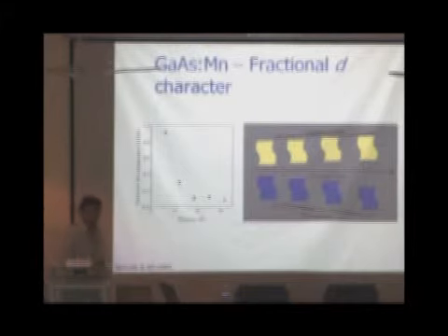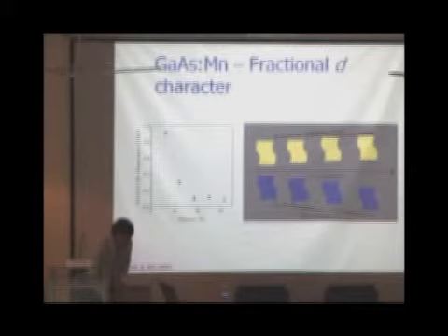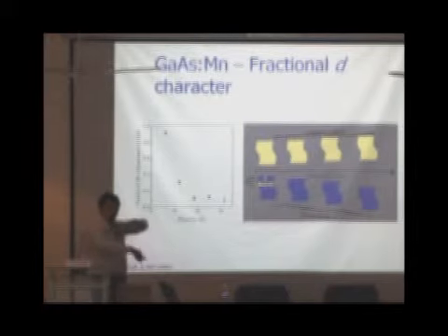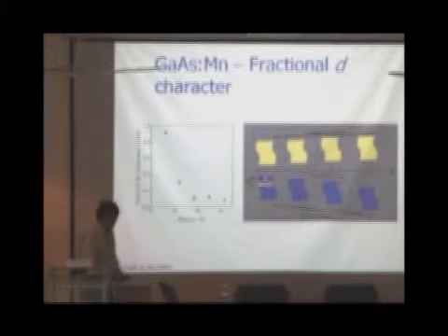it seems to drift. I'll just schematically explain that. So that's like 5d electrons of manganese over there, manganese 2 plus goes into gallium 3 plus, arsenide 3 minus. So it's a hole doped system. We have just 4 electrons, 1 for the hole. Since this is lying deep in the valence band, it can't be hole doped. So the hole has to float to the top, so the hole comes on the top.